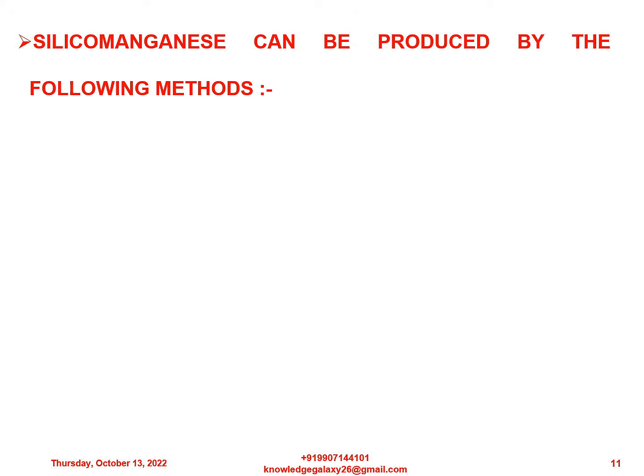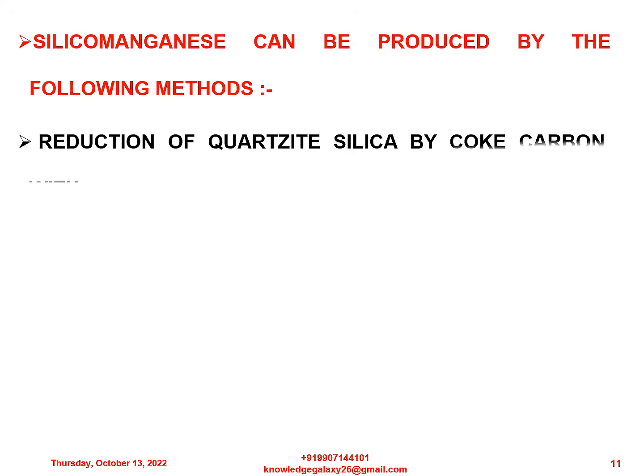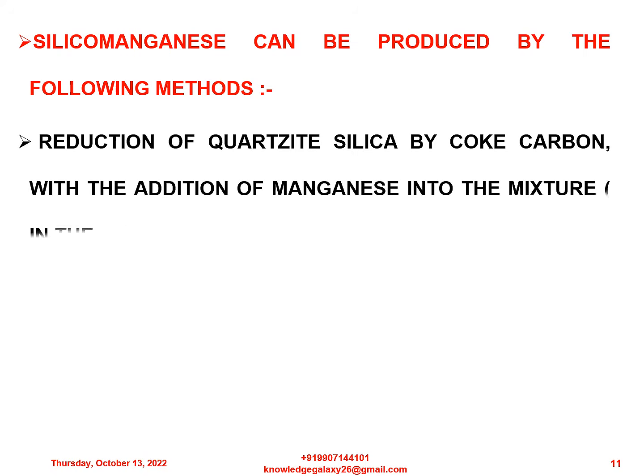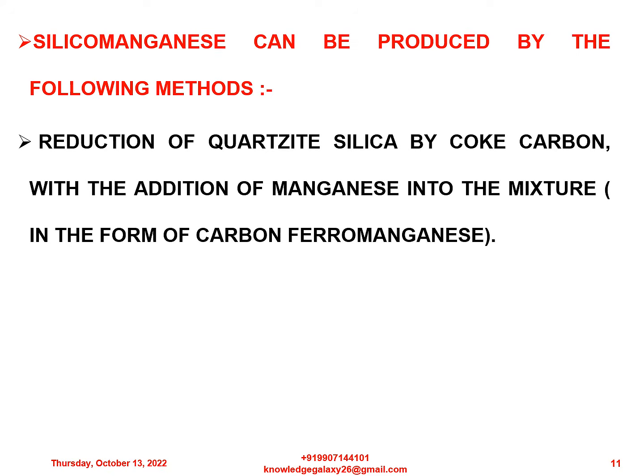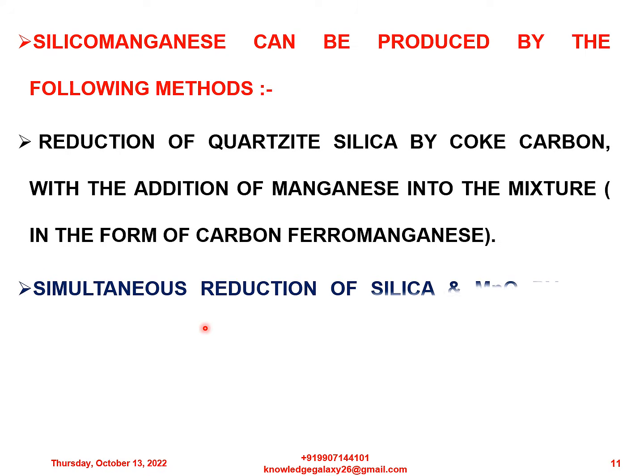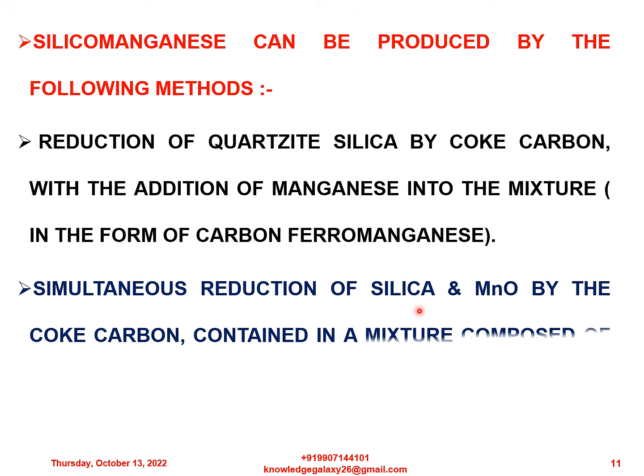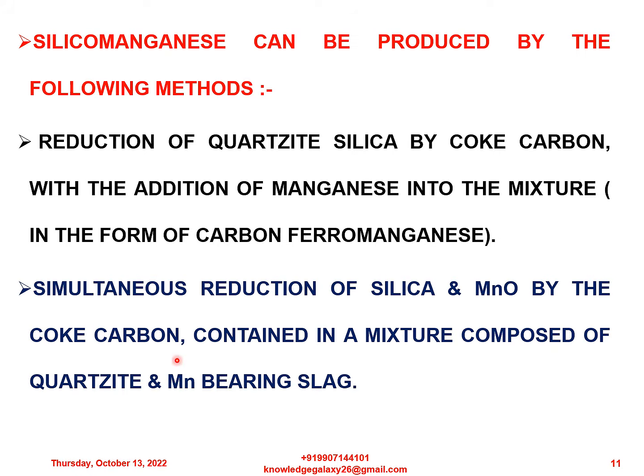Silicomanganese can be produced by the following methods. First, reduction of quartzite silica by coke carbon with the addition of manganese into the mixture in the form of carbon ferromanganese. Second, simultaneous reduction of silica and MnO by the coke carbon contained in a mixture composed of quartzite and manganese bearing slag.